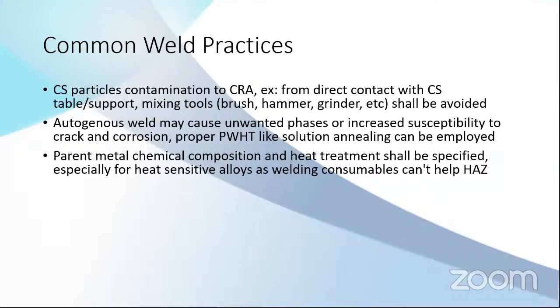The parent metal chemical composition and heat treatment shall be specified before creating the welding specification, because for some heat sensitive alloys, chemical composition is very related to the HAZ. If you have a very bad chemical composition, you can get very bad heat affected zones, because welding consumables cannot help the heat affected zones. They only help the weld metal, the fusion zone, but cannot help the heat affected zones.